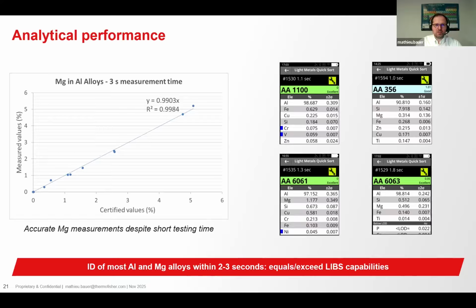And in this way, as you can see on the right-hand side, we can also differentiate some grades that are mostly differentiated based on the light elements, such as, for example, the grade 1100 from the grade cast aluminum 356 from 6061 and 6063, that differ mostly upon their concentration of magnesium and silicon. So in this way, we can identify most aluminum and magnesium alloys within the first 2 to 3 seconds, and this equals or even exceeds the capability of LIBS, given additionally that LIBS often needs several measurements to be done to compensate for heterogeneities.